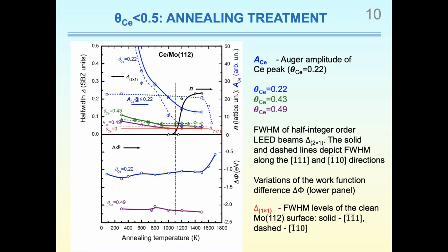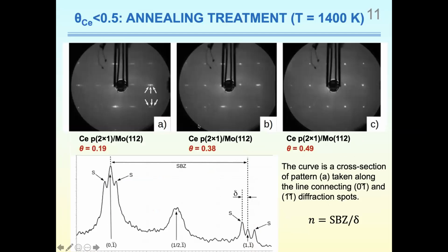At moderate annealing temperature, the ordering across the furrows proceeds markedly easier, as you may see by the relation between half-widths in direction of -1,-1,1, the solid line, and -1,1,0, the dashed line. The spot anisotropy, and thus a direction-sensitive deviation from order, is more expressed at lower coverages. It persists even up to the highest temperature annealing in the coverage range less than 0.4. The anisotropy of half-integer order spots is clearly visible in patterns A, B, but completely disappears in pattern C.